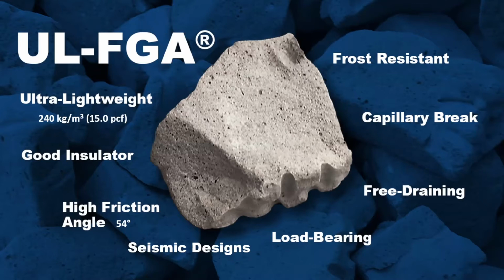What we mean by that is you can see the surface. There are bubbles, obviously, on the surface of the aggregate. There are bubbles on the inside as well. But with the closed cell foam glass, those bubbles are not going to be accessible by water on the exterior of the particle. So water is not going to be absorbed into a closed cell piece of foam glass and then freeze and crack up the aggregate or anything like that. So we're a very durable material in that way.